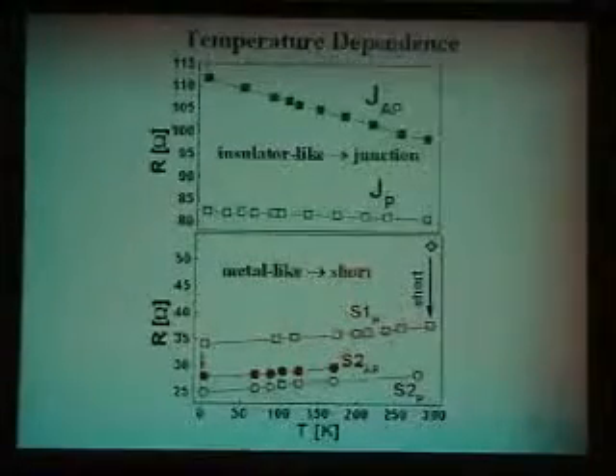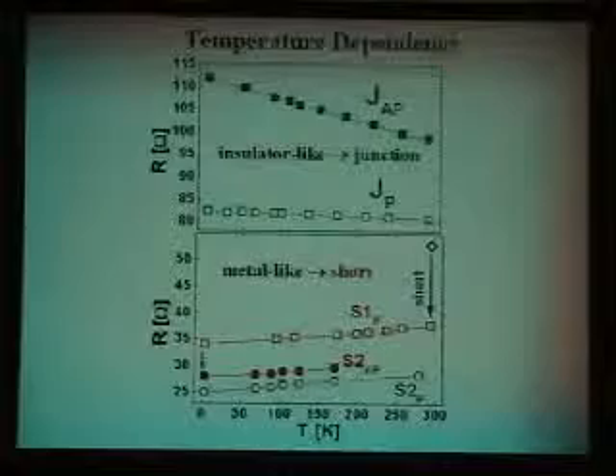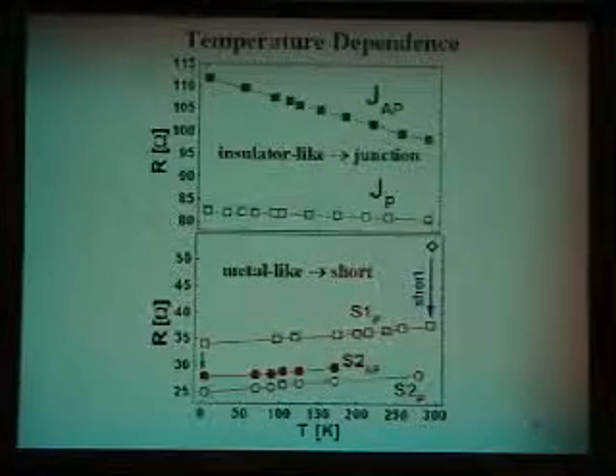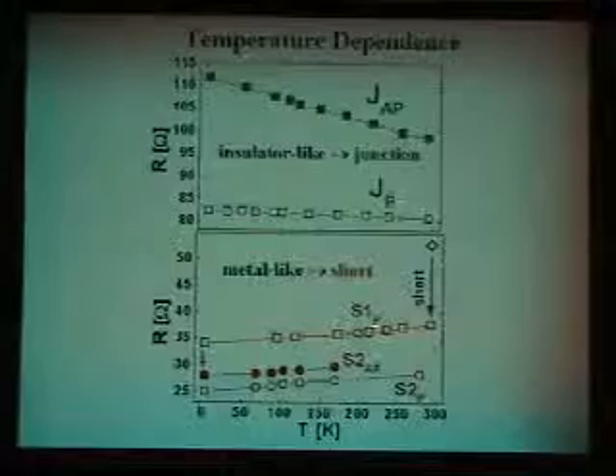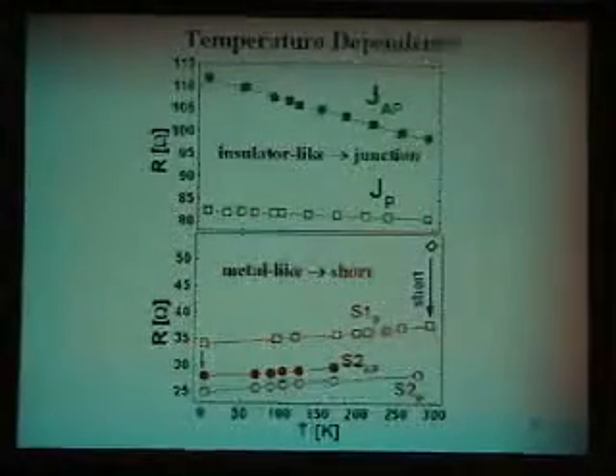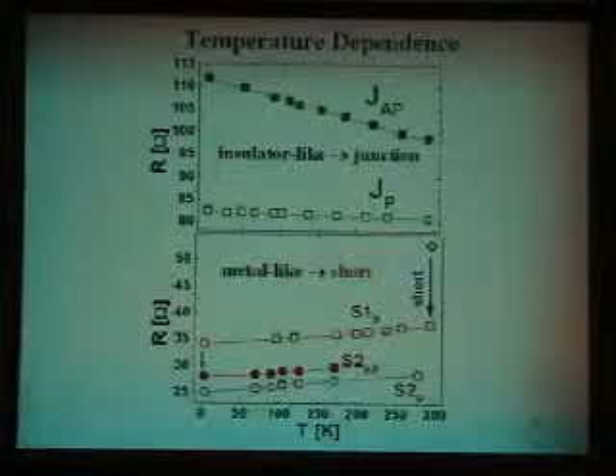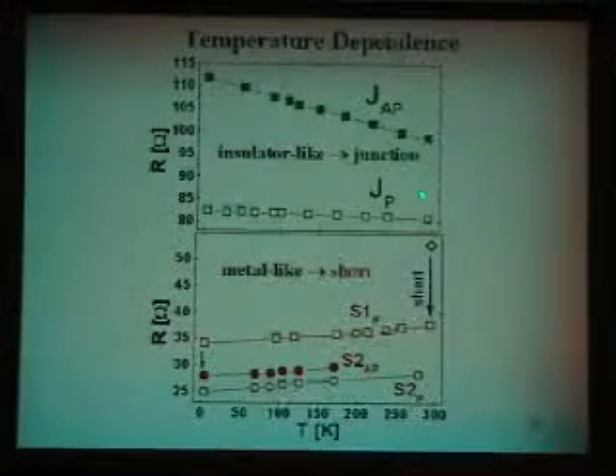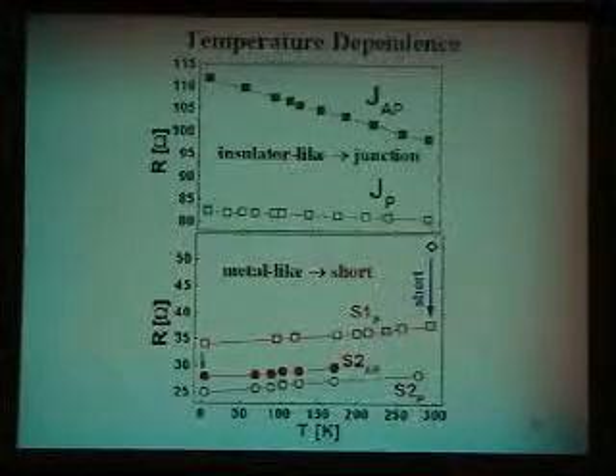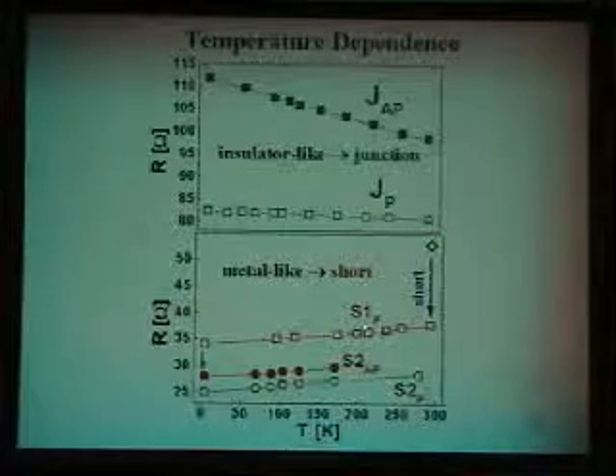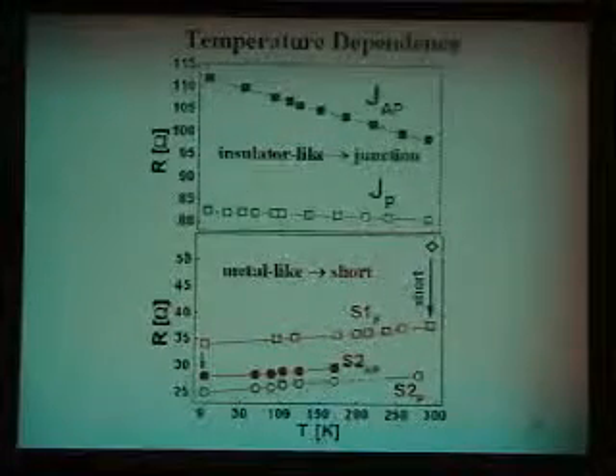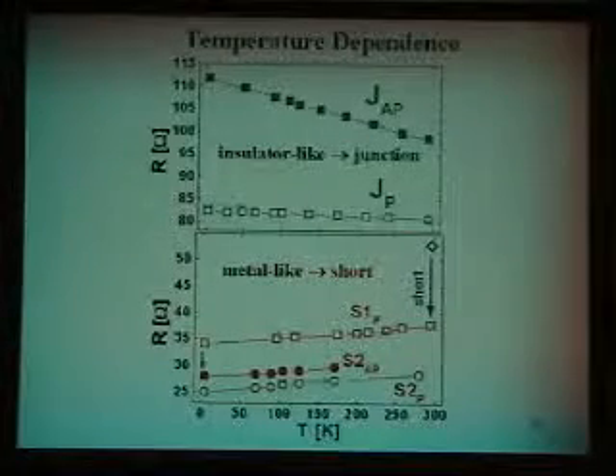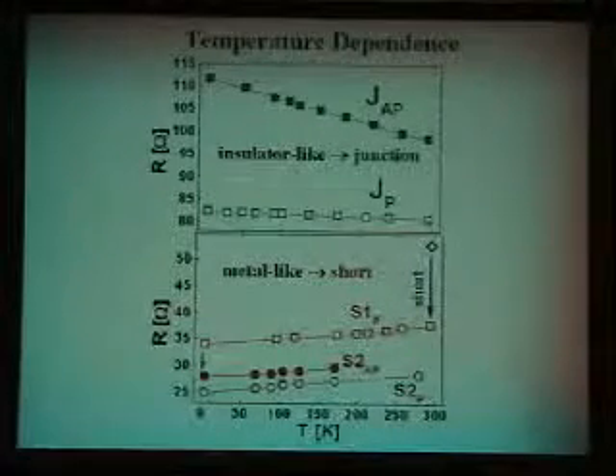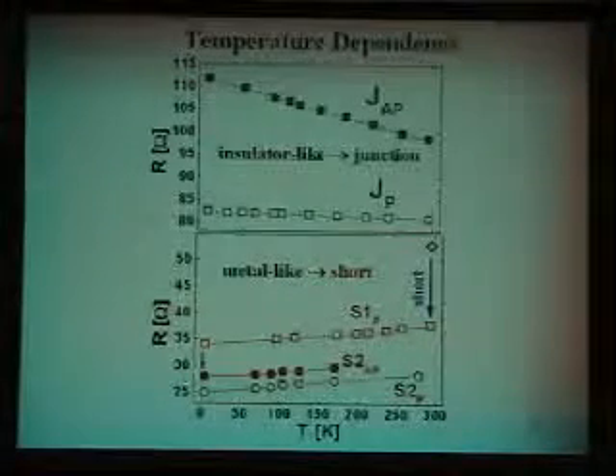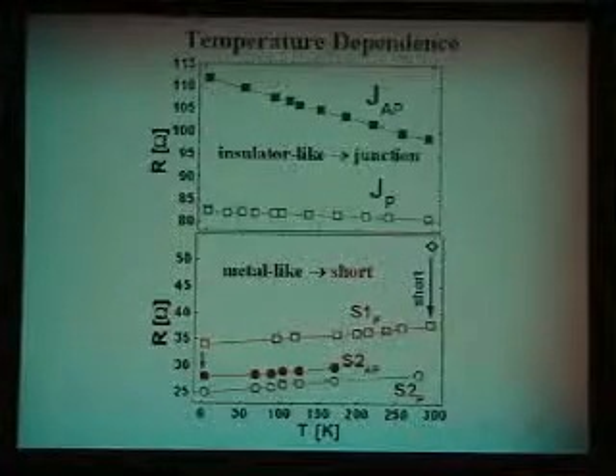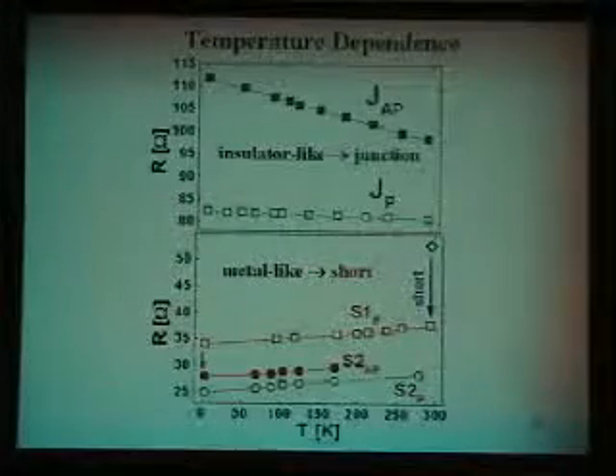And now what you do is you short it, you zap it. I mean, it's a very uncontrolled kind of thing, but you zap it, you know what can happen. It's not going to become better. It becomes worse, you see. The resistance drops, it does exactly what you expect it to do. When you short it, you make a small little metallic contact. The small little metallic contact has a lower resistance, and it has a different temperature dependence, the opposite of this one. Okay? And then if you short it again, it does the same thing again. So you go here, you short it, you go there, zap it, and you see this kind of behavior. So this is great. It does exactly what you would expect it to do.